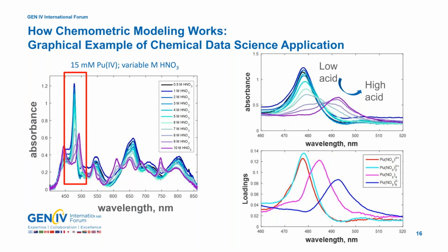Now, this makes sense. We know why this band shape change happens as we increase acid concentration. It's because we're changing the speciation of plutonium-4. We're going from the mono to the di to the tetra to the hexanitrato species, and we see that our model is actually pulling that out. It is pulling out the chemistry of the speciation transition and using that to identify and quantify the plutonium-4 present.